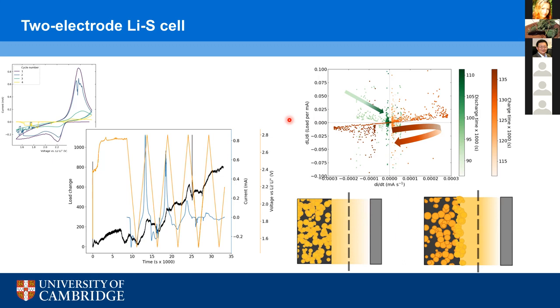However, there is this kind of linear, steady increase in pressure with cycling and the non-ideal electrochemical performance of the cell that you can see. Initially, because of the spiky voltage profile, normally I would associate this with forming lithium dendrites. In a lithium sulfur cell, the anode is always elemental lithium or lithium metal, which is different from a lithium ion battery where the anode is lithiated graphite. So it's quite easy for dendrites to form. Also, this voltage profile is similar to the cells I tested previously where a low pressure was applied, which is also conducive to lithium dendrite formation.